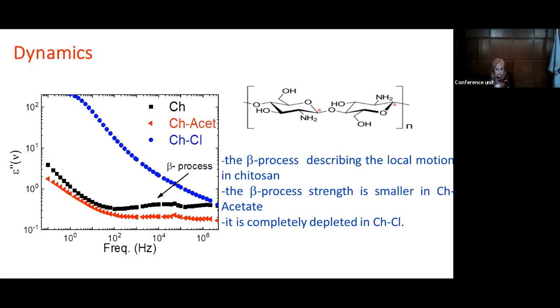For the chitosan-based acetate derivative, the intensity of the beta process is diminished a bit, while for the chitosan-based chlorine group, it is roughly depleted. This means that the ions moving around in the chlorine derivative already mask the local motions.